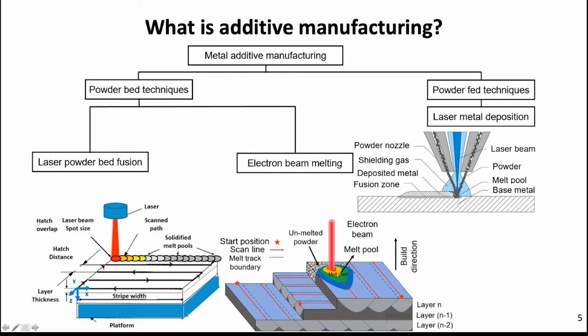Now, how does this work? You have a laser. The laser is focused onto the powder bed and is scanned through, and it leaves behind a trail, which is a solidified melt pool. Here you see that the laser can move towards the left and then towards the right. This zigzag kind of scan strategy is one of the many that is available. There are a number of parameters to which I'll refer in a moment, but the scan speed is an important parameter, such as the hatch distance and the layer thickness.